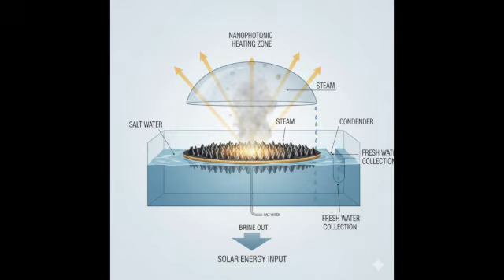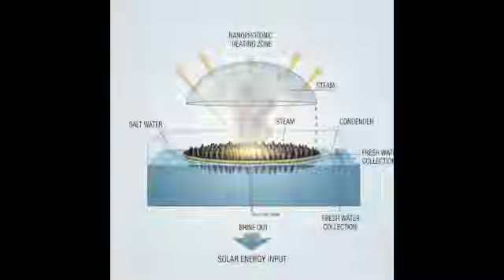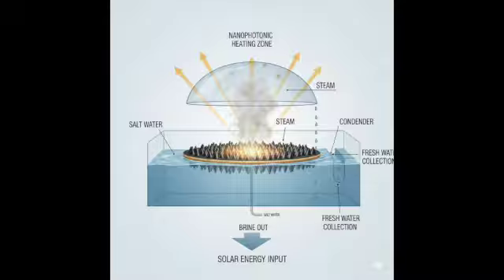But hydrophobicity alone isn't enough. You need to consider the liquid entry pressure, or LEP. LEP. That sounds like the pressure needed to force liquid water into the pores, which you definitely don't want. Exactly. It's a critical measure of the membrane's resistance to wetting under operational pressure. For reliable MD operation, you generally need an LEP greater than, say, 2.5 bar. What determines the LEP? It's governed by the Laplace equation. Essentially, LEP is proportional to the liquid's surface tension and the cosine of the contact angle, and inversely proportional to the maximum pore radius. Okay, so LEP equals B gamma cos theta over r max, where B is a geometric factor.